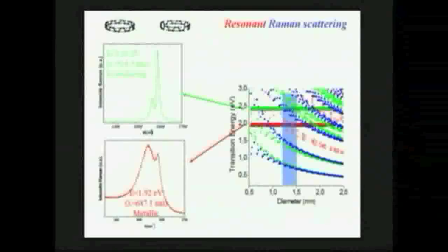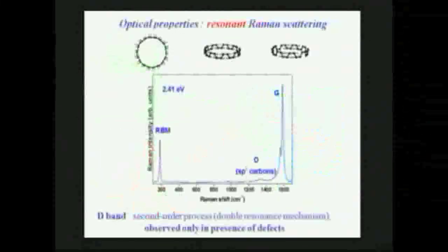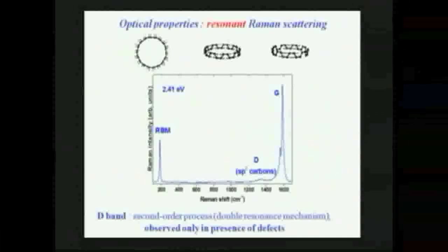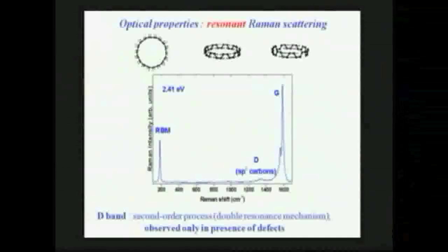The first ones were this carbon-carbon stretch that we also call G-band because you can see the same peaks in graphite. So G refers to graphite. We call this CC stretch, carbon-carbon stretch, G-bands, because you observe similar signatures in graphite. This is not the only interesting contribution to Raman. There are at least two other widely used peaks to characterize nanotubes.